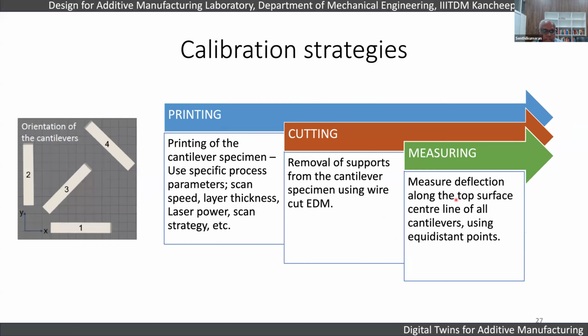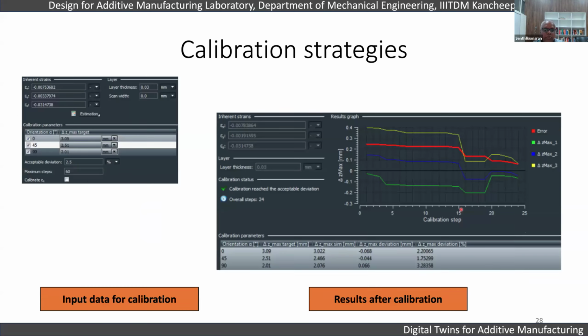So the calibration happens like this. You print the cantilever specimens along multiple directions, like parallel to X, parallel to Y, 45 degrees, and also 135 degrees and things like that. You can change the scan speed, layer thickness, laser power, scan strategy. And then once you remove the supports from the cantilever using wire EDM and you remove it from the build platform, it will deflect. Measure those deflections along the top surface, along the center line of the cantilever, using equidistant points for each of these cantilevers, and then input that into a calibration software.